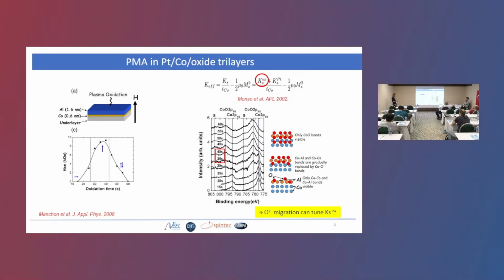So in the case of, for example, platinum cobalt 0.6 nanometers covered by aluminum, by oxidizing it differently, if they don't oxidize it, they have in-plane anisotropy. If they start oxidizing, then the magnetization goes out of plane, so the anisotropy increases. They get a maximum, and then they go to what they call the over-oxidized state. Then the anisotropy decreases, and then you can get to a multiple domain state or in-plane state.